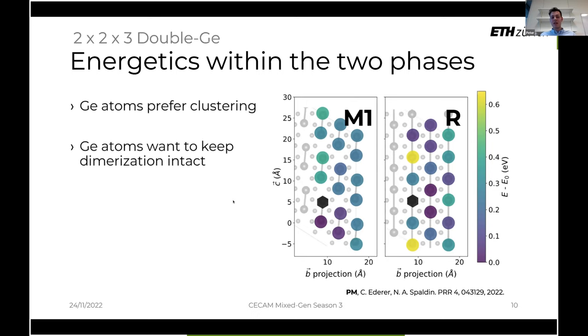The next thing to note is that germanium atoms, as they organize in the cell, seemingly want to keep the dimerization intact. Indeed, one can see this in the monoclinic phase, where the energy of occupying the other dimer site, so filling the whole dimer with two germaniums, is markedly lower than starting to fill another dimer with a germanium. So breaking two dimers costs way more energy than breaking just one and occupying the other site with germanium.